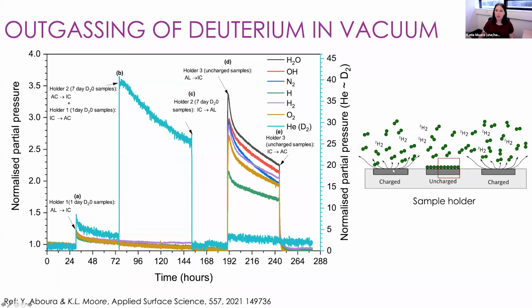In hindsight, we actually think that this may have been somewhat beneficial for us, because if we had frozen our sample and analyzed it in cryo conditions, all of the deuterium that we had charged into our sample would have still been present. We may have only seen a uniform deuterium image on the top surface, as all the deuterium would have still been there in the bulk. But by allowing the sample to outgas a little bit, it has improved our contrast. And it's left behind the deuterium that's in the trap sites, which is what we wanted to investigate anyway. So we may have actually been very lucky here by not having a cryo stage.